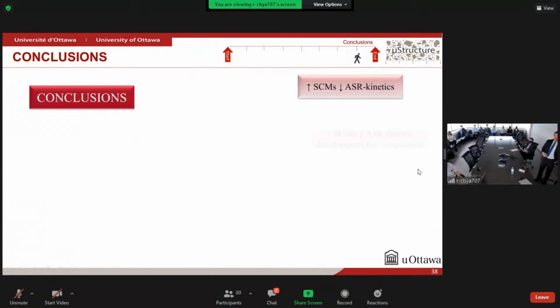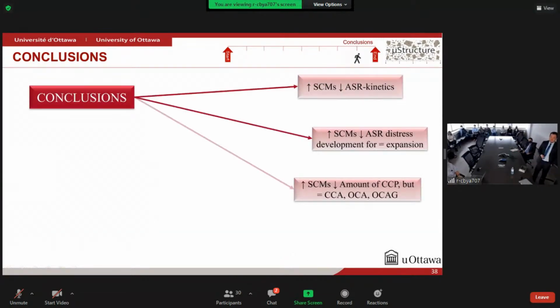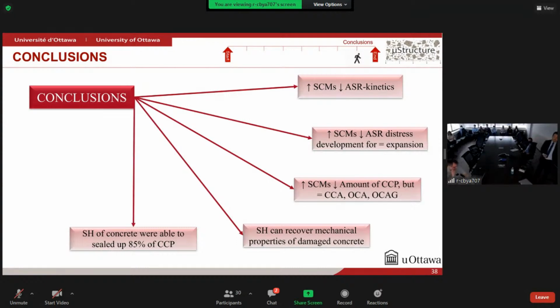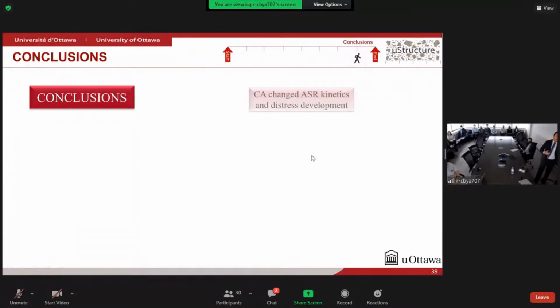In conclusion, increasing the amount of SCMs, there's a decrease in ASR kinetics, also a decrease in the distress development for equivalent expansion, and a decrease in the amount of cracks in the cement paste, but the amount of cracks in the aggregates is the same. This behavior can be explained by the fact that self-healing can recover mechanical properties of damaged concrete, and it was proved that self-healing of concrete was able to heal up to 85% of the cracks in the cement paste. Moreover, this proved that crystalline admixtures can indeed change ASR kinetics and distress development.